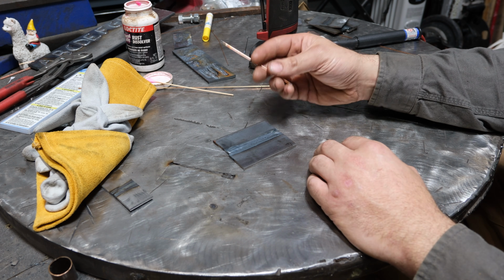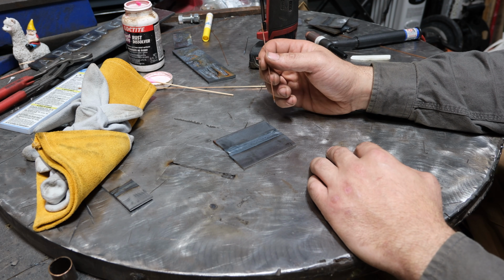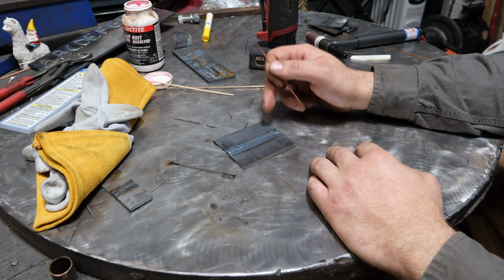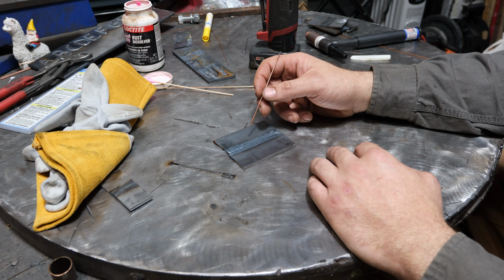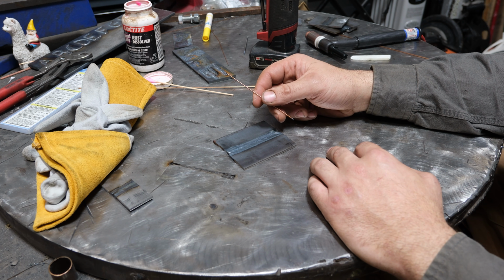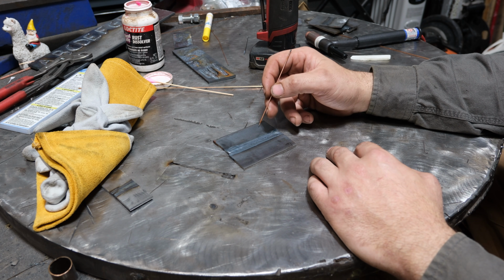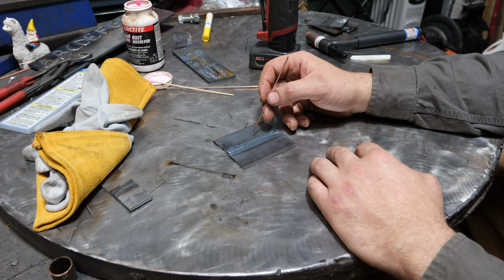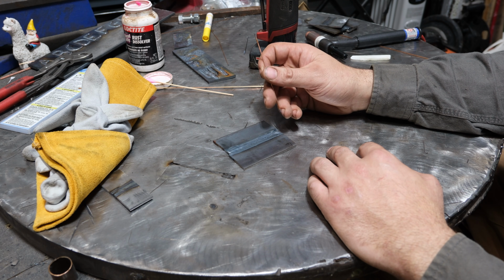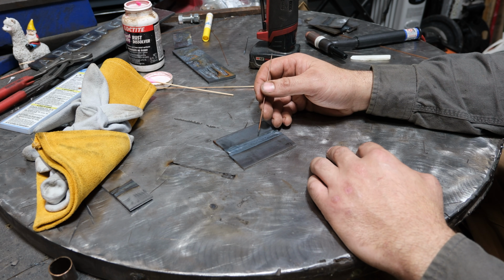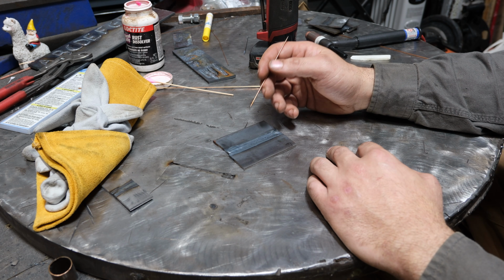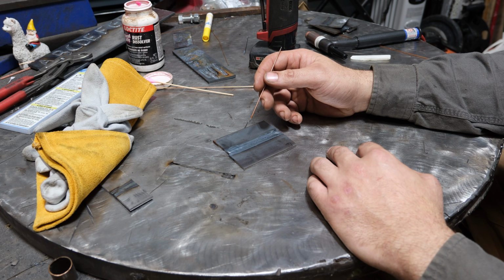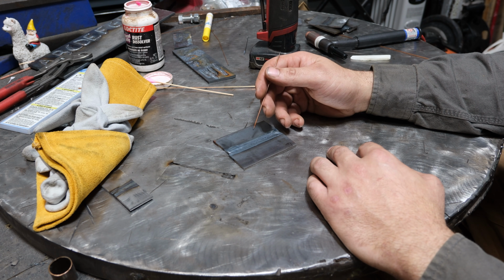And speaking of filler rod, these filler rods are an alloy. They're not just the same material as the base material you're welding, and they have what's known as deoxidizers. By doing fusion welds, your ability to join material with defect-free welds becomes diminished because there are no deoxidizers being introduced to the molten pool. So it's always in your best interest to use filler material to join two pieces.